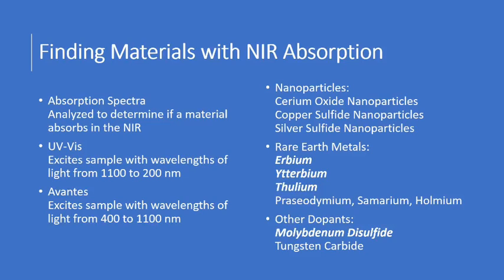So we had to look at their absorption spectra. Absorption spectra shows how much of the light is absorbed versus what wavelength it is. We used two different machines to do this. One was the UV Vis, and one was the Avantes. The UV Vis excites from 200 nanometers to 1100 nanometers, while the Avantes excites from 400 nanometers to 1100 nanometers. What's good about the Avantes is even though it has a smaller range, it gives us much clearer depictions of what's going on, so we can see more peaks there, but the UV Vis gives us a wider range.